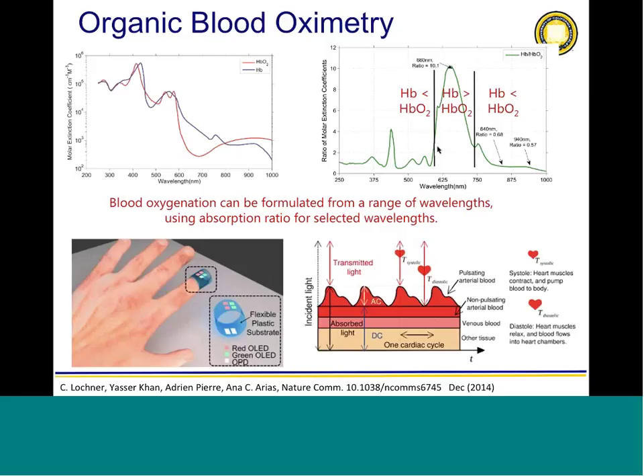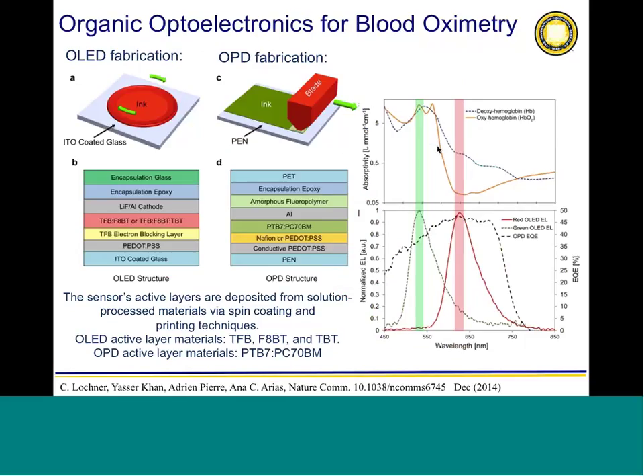If you don't want pulse oximetry, you just want to know the saturation of oxygen in the blood, then you can measure in other locations where you don't have the pulse. But you always need the pulse to calibrate your measurement, and I'll go back to that later in my talk. So we went back to organic electronics, and since people worked so hard to make nice displays, which by the way is going to be in the new iPhone with these organic materials, we picked a red and a green LED, mostly because there was no infrared material available when we started working on this.